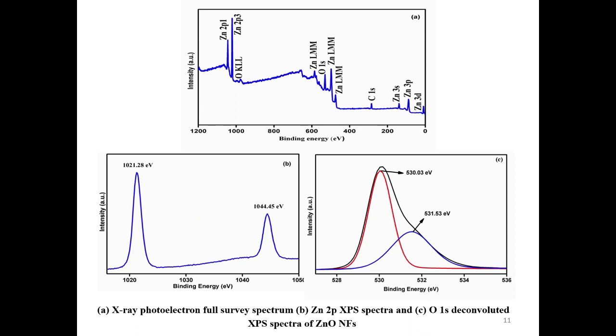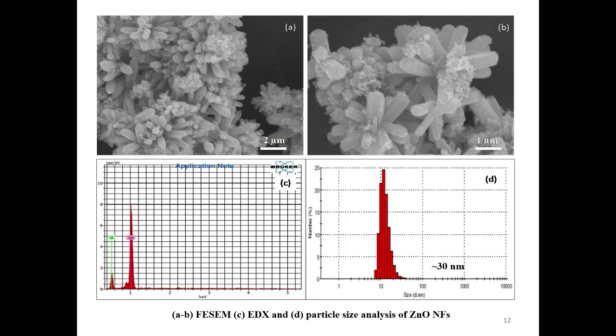This is the X-ray photoelectron full survey spectrum, the zinc 2p XPS spectrum and the oxygen 1s deconvoluted XPS spectrum of zinc oxide nanoflowers. The oxidation state has been determined here, and the binding energies for zinc and oxygen are observed from 1021.28 electron volt and 1044.45 electron volt. These are the SEM images, and the images themselves show the formation of the nanoflowers. Complete nanoflowers are formed during the synthesis of zinc oxide nanoflowers. The EDX shows that pure zinc oxide crystals are present in the material. Particle size analysis was also done, and it was found to be 30 nanometer.